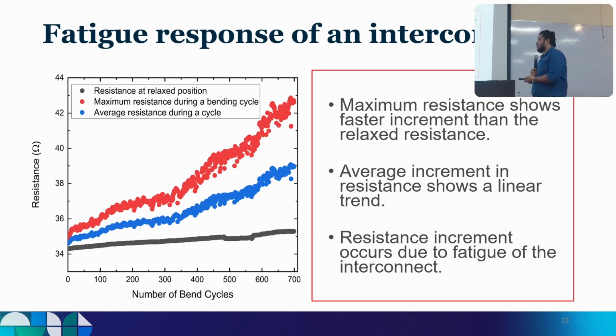Alright, this is one sample of results. This is just a single interconnect bent over about 700 cycles. In red is the maximum resistance during a single bending cycle. The bending cycle, as I explained, was the machine going up and downwards. The maximum resistance occurs at the top because that is where the maximum bend and maximum stretch occur. The line in grey or black is the resistance recorded at the rest position, so the interconnect is at rest, with no bending. And the blue data points are the average resistance over a cycle.